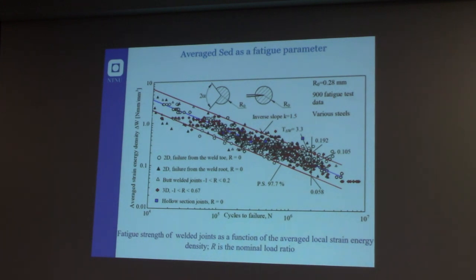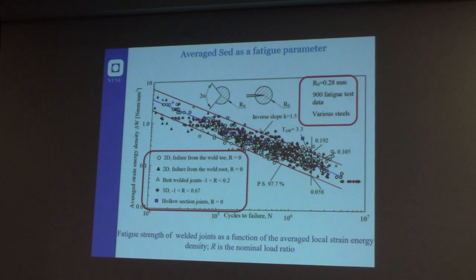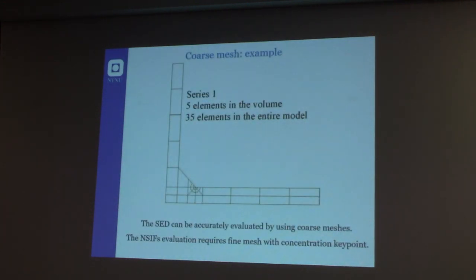Actually, considering failure occurring from the weld toe and weld root, we were able to summarize more than 900 fatigue data for weldments in a single scatter band that can now be used for design purposes, at least for steel, if you consider a critical radius of 0.28 millimeter. So the advantage of the approach is that you can use a very coarse mesh.